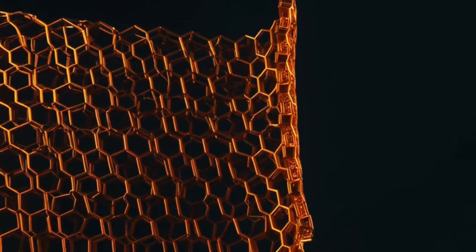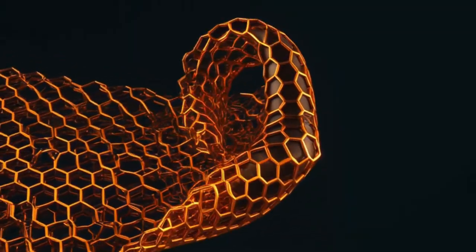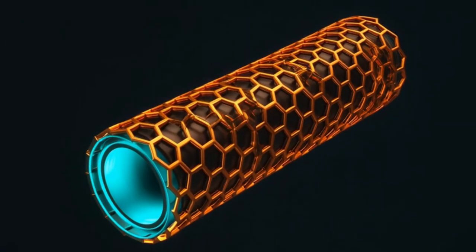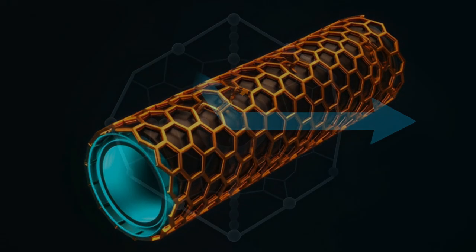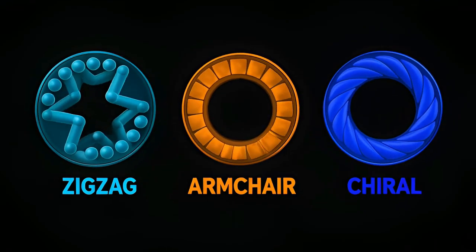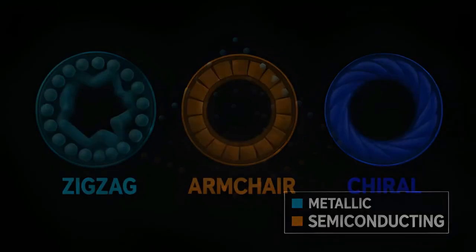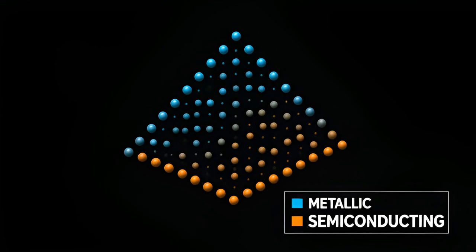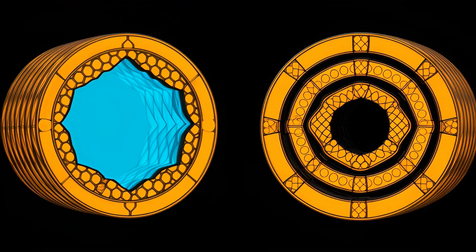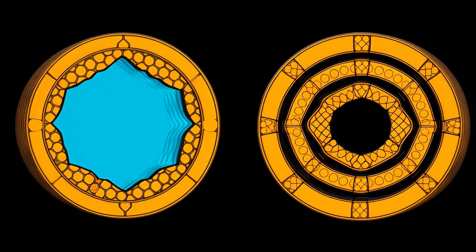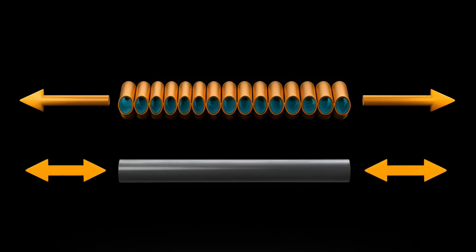And if you roll that graphene sheet into a seamless cylinder just one atom thick, you create a carbon nanotube. The direction in which you roll it determines everything. It alone decides whether the nanotube conducts like a metal or a semiconductor. Whichever direction it takes, the resulting nanotube has a tensile strength of 150 gigapascals, while steel manages just 0.4.